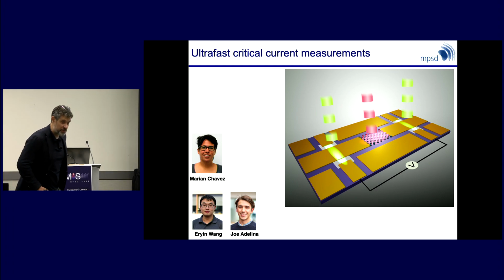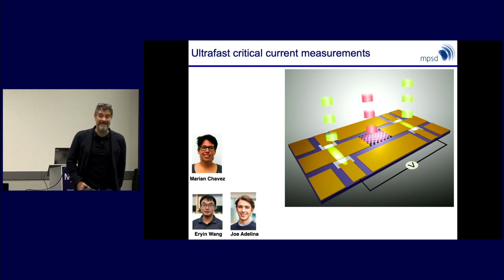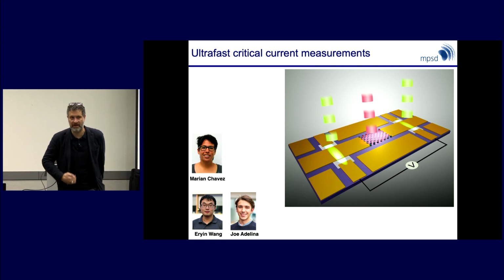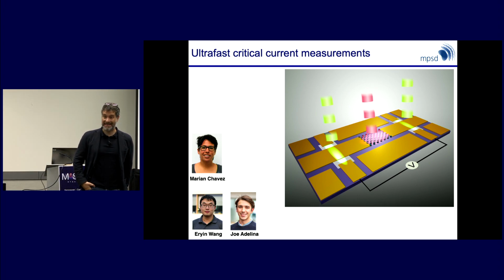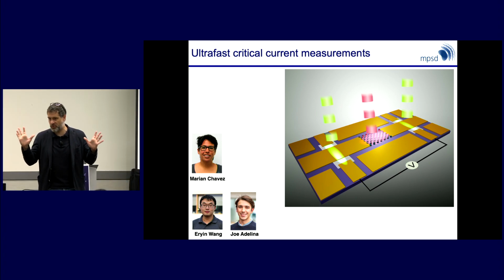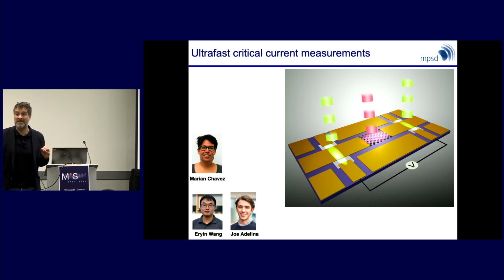Okay. So the metastable life, with the caveat that we haven't characterized everything, the experiment is just hard enough that we haven't been able yet to characterize it. The metastable lifetime is long, but it seems to depend a little bit on the phases of the moon, but it doesn't change very much. The point that I would like to make to your question is that we don't think that the relaxation rate is determined by dissipation of heat. Right? But rather by some rate-limiting timescale.